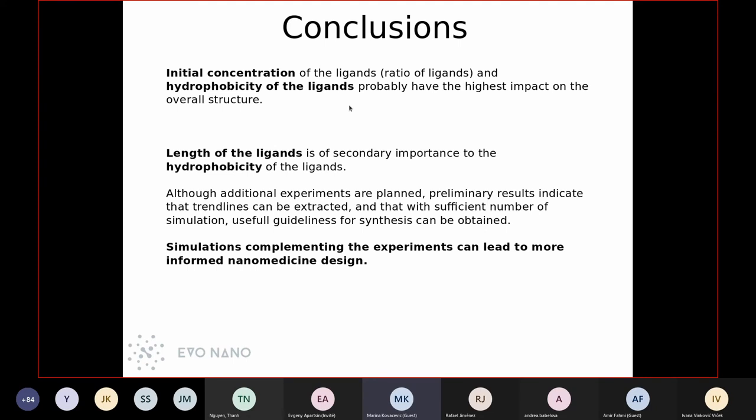And to what extent the structure will be changed depends on the initial concentration of the ligands, because the number and the type of interactions will change. Length of the ligand is of secondary importance, and we saw that both in the example of hydrophobic and hydrophilic drug, because although background ligand was shorter in both cases, it still ended up covering a good part of the surface.